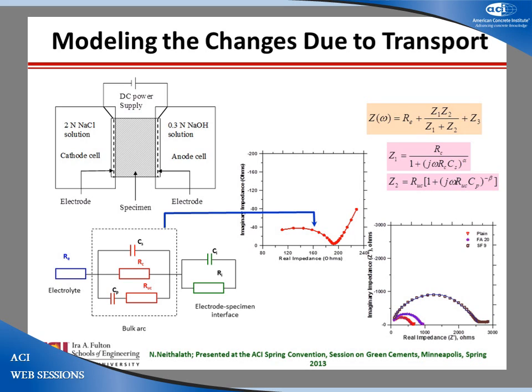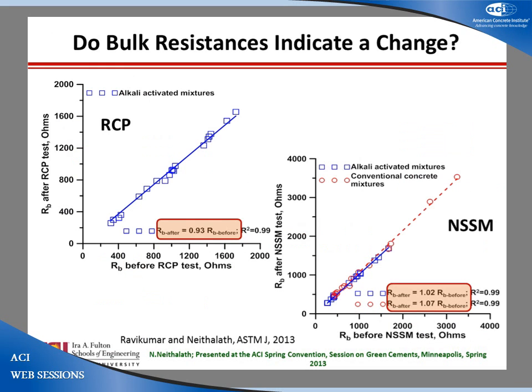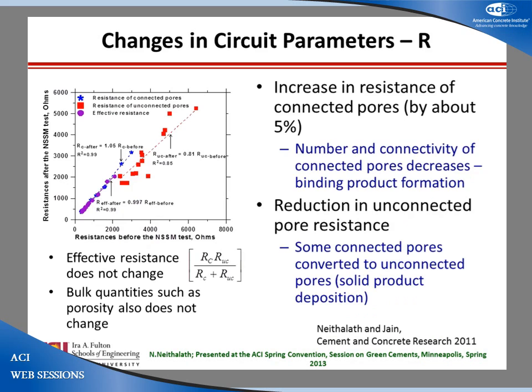So basically what you can say is my specimen now is just a combination of resistors and capacitors. The pore solution, the pores are the resistors, the solid phases and the interfaces are the capacitors. So if I use that kind of an analogy, and then if I look at bulk resistances alone before and after RCPT or the non-steady state migration test, you can see that generally after the RCPT test the bulk resistances come down, whereas after the non-steady state migration for a longer period of time your bulk resistances slightly go up. And I'll talk to you more about why that happens.